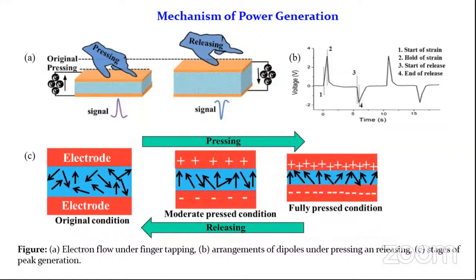Look at the nature of the peaks. We can see that at position one, we are just pushing the piezoelectric composite. At position two, the composite feels the maximum strain. That's why we are getting that much voltage. At position three, the material undergoes release of the pressure, and at point four, the material is at the end of the release of pressure.